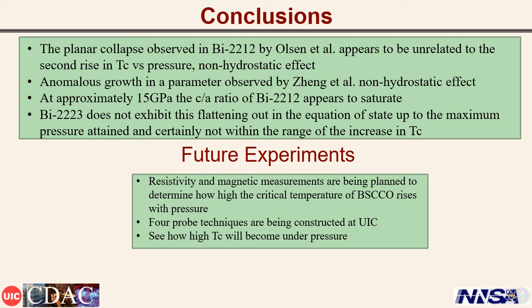BSCCO 2223 does not exhibit this flattening out in the equation of state up to the maximum pressure attained, and certainly not within the range of the increase in Tc. We are currently preparing transport experiments to see how high we can raise Tc in both BSCCO 2212 and 2223.